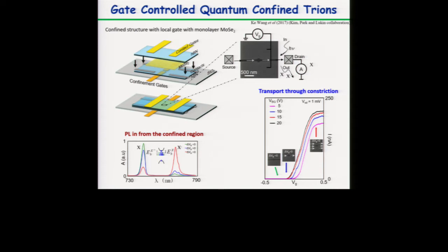So we have made quantum dots on a single layer, so we can optically drive them. We can optically look at PL. This is the PL from the quantum dot area. We see the neutral exciton. We also see the charged exciton. But there are two peaks. There is a big peak that will be the delocalized trion peak. And then there is this small peak, which is like a localized trion peak.